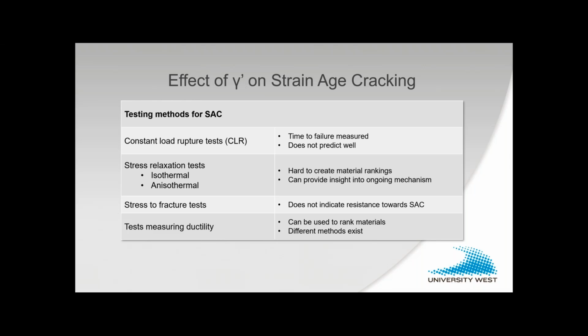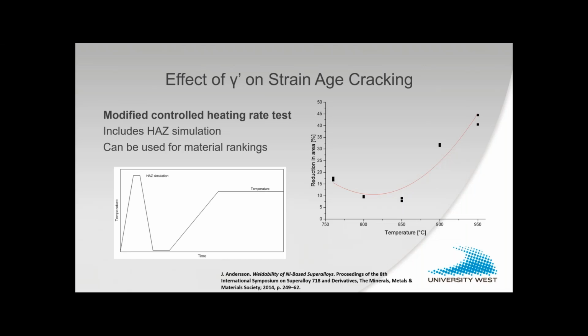And my favorite are the tests referring to measuring of ductility. These type of tests can be used to rank materials, and there are different methods. So the ductility type of test is what my former student Fabian Hanning went into. Quite some years back, I saw a test. I think it was Metzler at Haynes International who developed it, and he did really nice work where he ranked different superalloys. And basically, what he did was to simulate a post-weld heat treatment cycle. And what you do is that you have a slow heating up to a certain test temperature or soak temperature, and then you slowly pull the sample to fracture, and then you measure the reduction in area and plot that versus the test temperature.